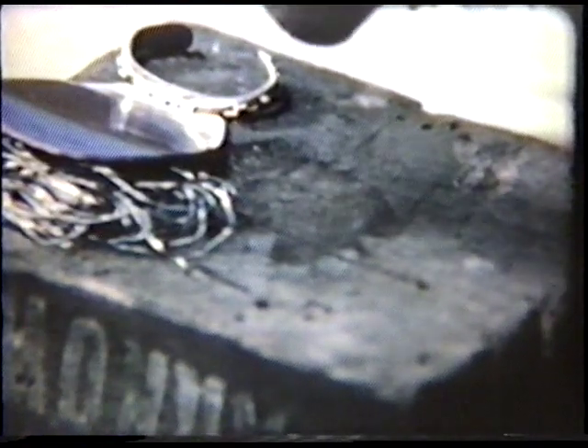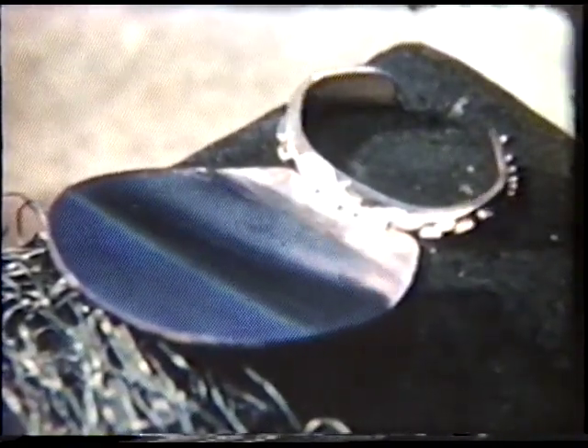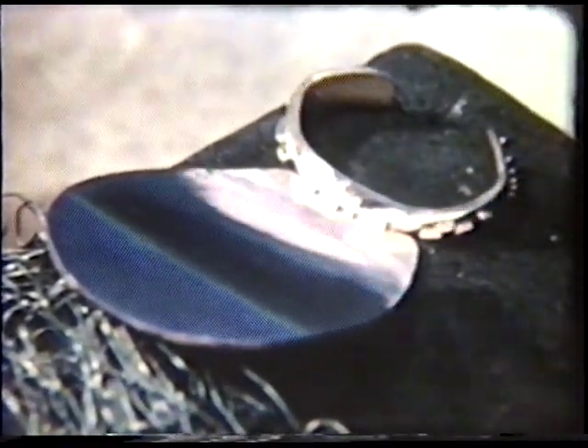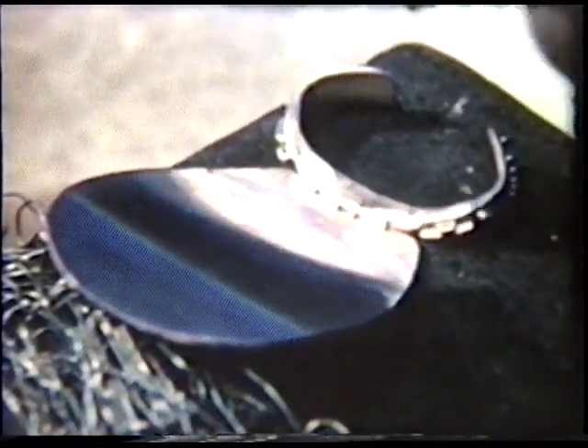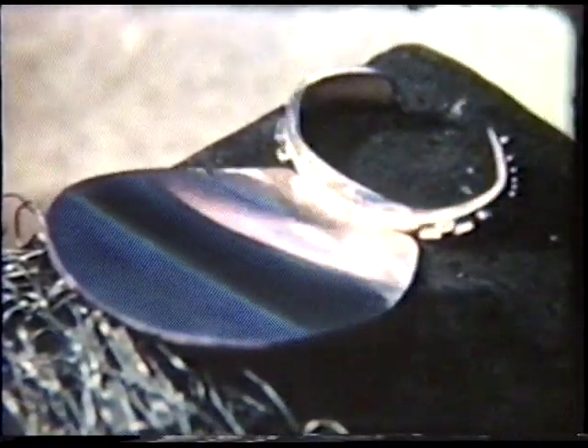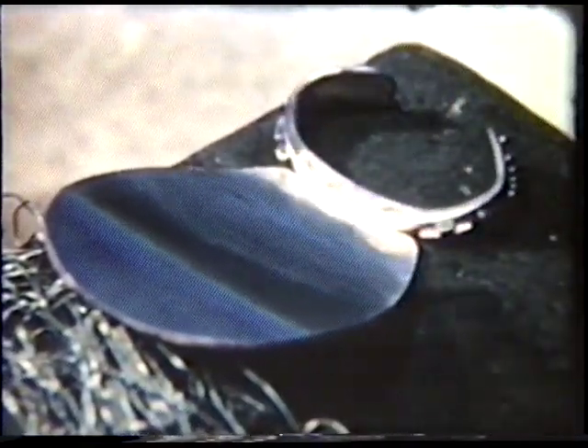Flux, a form of borax, forms a protective coating which keeps the oxygen in the air from developing oxides on the surface to be soldered. These oxides would prevent the solder from flowing when the metal is heated. This solder melts at 1490 degrees and flows through the joint by capillary action. After soldering, the piece is cleaned by immersing it in a hot dilute solution of sulfuric acid.